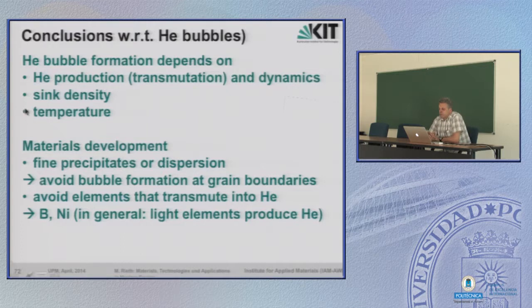And with respect to materials development, we want to have many and finely distributed precipitates or dispersions. This will avoid the bubble formation at grain boundaries, which causes these dangerous brittle fractures. And in general, you have to avoid elements that directly transmute into helium. Typical examples are boron, also nickel, and unfortunately only 2 or 3 iron isotopes. So in general, light elements produce helium, and in steels and most other materials, you cannot avoid using one or other light elements. That's why we in general have to live with the helium bubble formation.